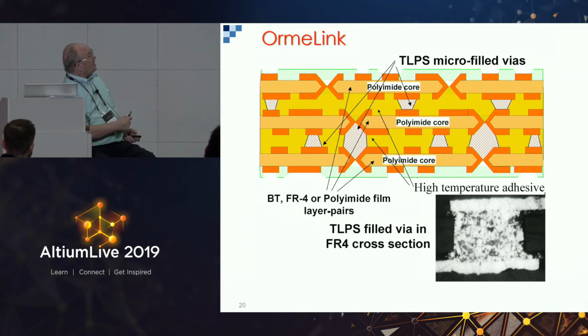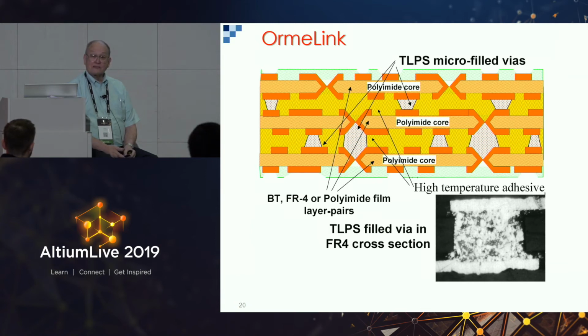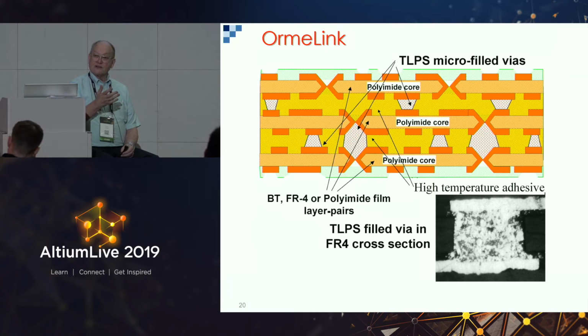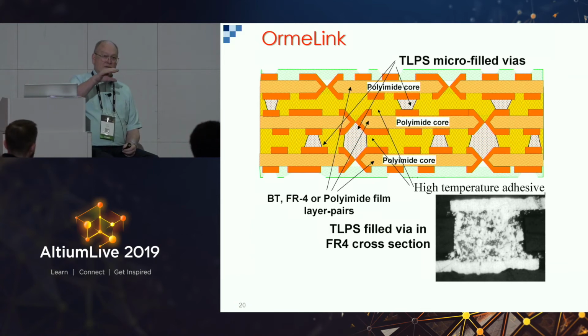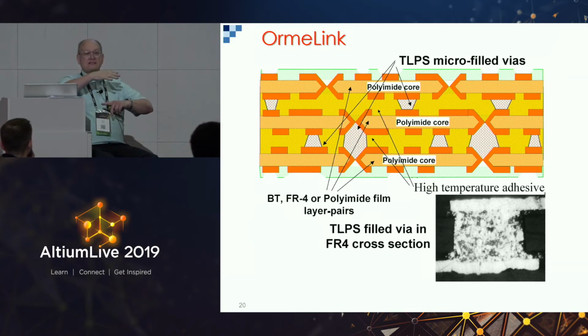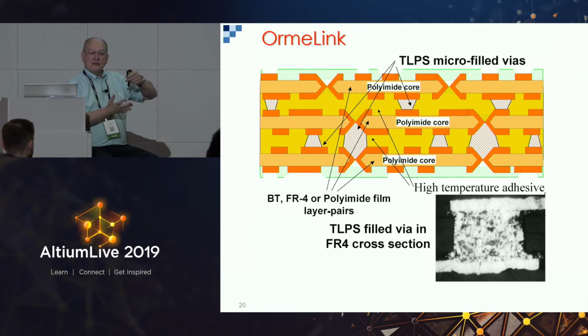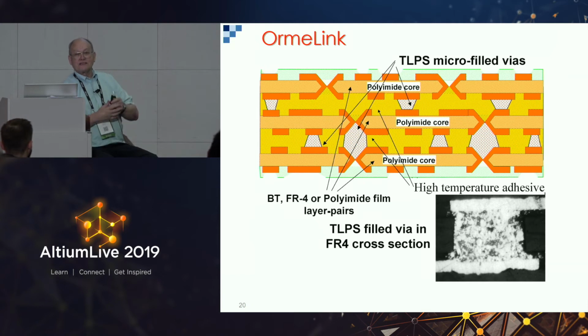So what you're looking at is 4 mil pads, well, 100 micron pads, 20 micron vias. This was manufactured 25 years ago. So this was high yield, high production, but this is 25 years old. So hopefully you've seen this before. If you haven't seen it before, you're not reading enough. Because it still runs today, and the company is still there. But most of it's been used by IBM. So IBM used it to make 60-layer boards out of Teflon and things like that. So the Blue Streak and all these massive big IBM machines, they're made out of 8 and 10-layer multilayers that are sintered together to be 60 layers. They're not made as 60 layers, they're made as 10-layer, and they use this transient liquid phase to sinter all the stack up to a total of 60 layers. That's how IBM does it.